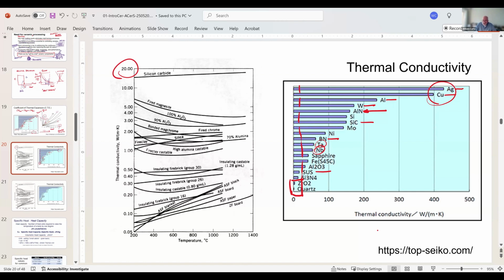And so what you see is that all of these materials are in this small area down here, okay, or this area, if you will, in this plot. And then we've differentiated. Silicon carbide's at the top. Here's magnesite, alumina, mag chrome from a refractory, fired chrome, silica, and then fire clays. And down here, you get into insulating materials. Insulating fiber bricks are here, these are castables, and this is then fibrous materials,